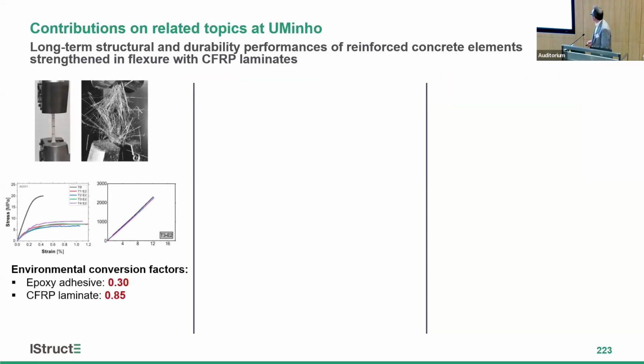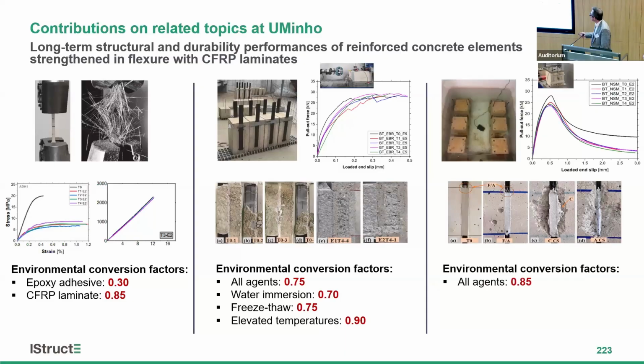And here, I only show a few results in terms of material level, bond scale. And here, one of the most important things that we would like to provide was conversion factors that are needed to consider durability of these systems over time. By the way, it is curious that the new Eurocode proposed the value of 0.7, which is in line with what we observe with the EBR, but for the case of near surface it is conservative because our value was 0.85.